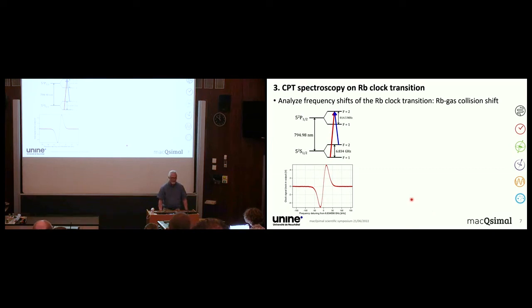Now, in order to characterize these cells, we turn to CPT spectroscopy on the rubidium clock transition, and the clock transition is connecting the 2 lower hyperfine components of the rubidium ground state, which is at 6.834 and some other digits gigahertz. And we can then sample this by a bichromatic laser light that we produce by modulating a laser beam using an electro-optic modulator. And this transition is then sensitive to the gas content in the cell due to the rubidium buffer gas collisional shift, and we measure the collisional shift of this clock transition. Here you see a plot of our signal against the microwave frequency, and we get a very sharp discriminator that allows us Hertz level resolution at 6.8 gigahertz absolute frequency.